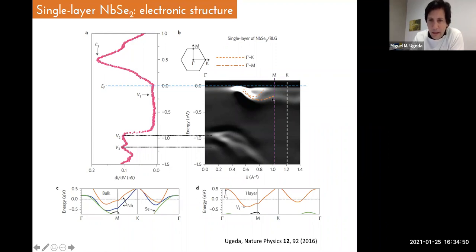And this is something that we had the chance to demonstrate using ARPES in the past. Here you can see the two pockets that cross the Fermi level. Here's one, here's another one. And even though we don't see them separate in space because niobium diselenide is rotationally disordered, we lose in ARPES our angular resolution. However, still we can distinguish these two electron pockets.